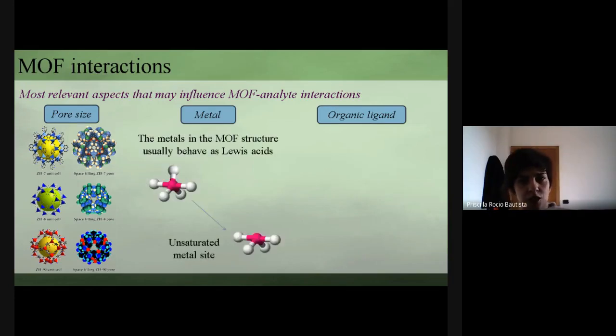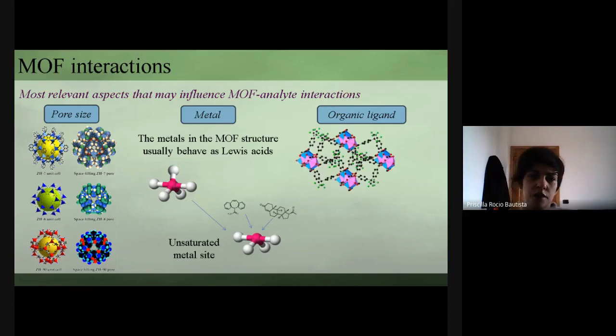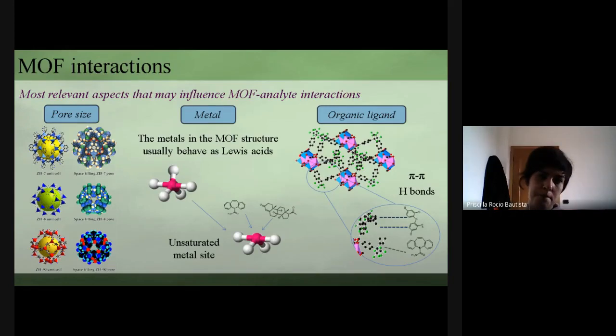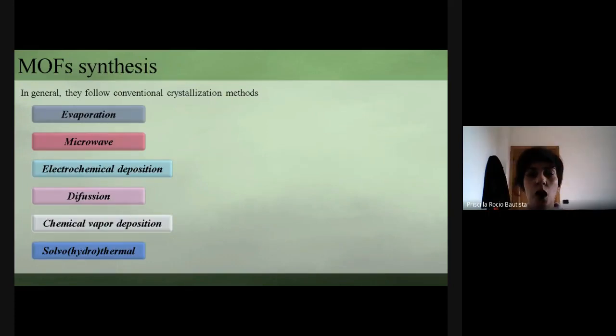The metal in the MOF structure usually behaves as a Lewis acid due to the presence of unsaturated metal sites. Therefore, they can be available for coordination with organic analytes. On the other hand, the organic ligand in the MOF structure commonly contains aromatic rings and carboxylate groups, able to experience pi-pi interactions or hydrogen bonds with the target analyte. In general, the preparation of MOFs follows conventional crystallization methods, such as evaporation, assisted by microwave, electrochemical deposition, diffusion, chemical vapor deposition, and the most widely used, the solvothermal reaction. Our research group will focus on solvothermal synthesis.